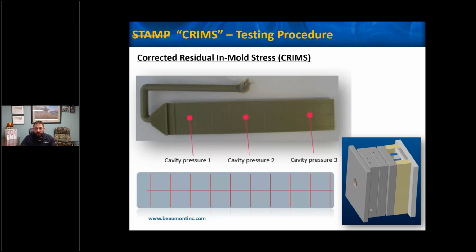And then step 5, a linear coordinate optical measuring device is used to take the actual dimensions. So really what that device is doing is it's evaluating the grid pattern from its initial CAD nominal position to any final resting position. So essentially it's shrunk down state. So we're evaluating a position that was CAD versus a position after shrink.